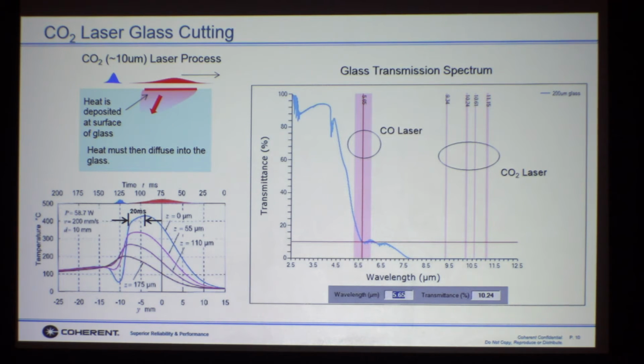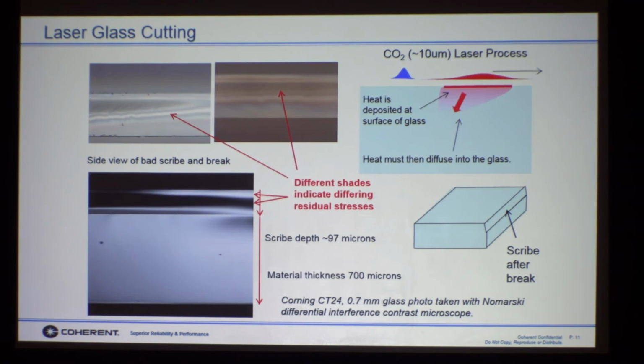And then the heat, which is used in the process of this stress cracking, or stress vent generating, is deposited into the bulk of the glass via diffusion. So you can see from this graph that it takes some time for the heat to diffuse from the surface down into the glass where it needs to be. And then that elongated CO2 beam is followed by a cooling jet, and that cooling jet creates the stress that's needed to create the vent.